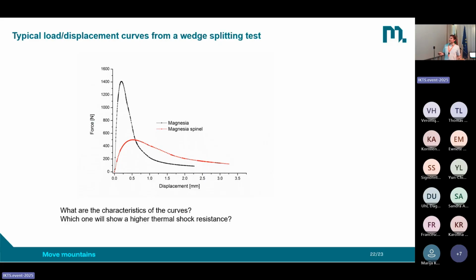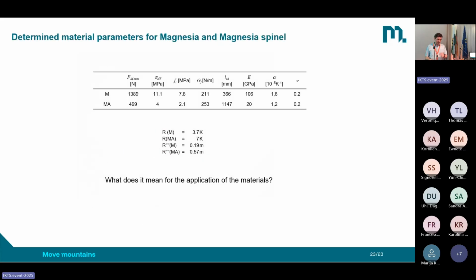And then some people may think about the area under the curve. If you compare then this one for magnesia and this one for magnesia spinel, you may get an idea that maybe it's more or less similar. So maybe the magnesia refractory is more thermal shock resistant. If we look now on our parameters, then it looks different. We have here the line for the magnesia refractories, where we see a tensile strength of 7.8 megapascal, quite usual for a magnesia brick. We have specific fracture energy 211 joule per square meter, and then we have this characteristic length 366, and the Young's modulus 106.